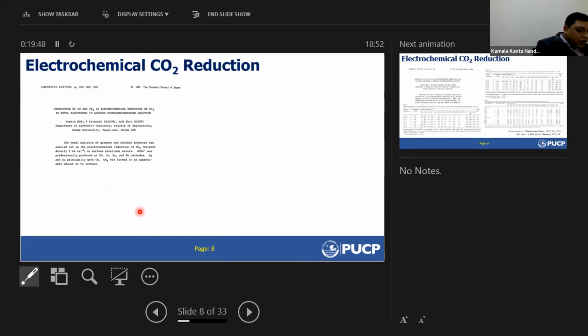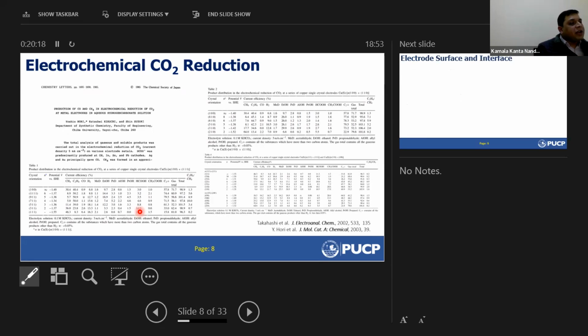Coming to my first work on electrochemical CO2 reduction: it was first reported by Hori in 1985, when they used a copper electrocatalyst and obtained syngas, methane, ethylene, and some hydrocarbons. Later, they tried a lot of metal electrodes and obtained different products on different metals. The best material for this is copper, because copper shows better selectivity towards C2+ products in CO2 electroreduction. That is the main aim, to obtain the C2 product. It depends on the binding energy of the metal to the intermediates. I am not going into much chemical or technical detail.